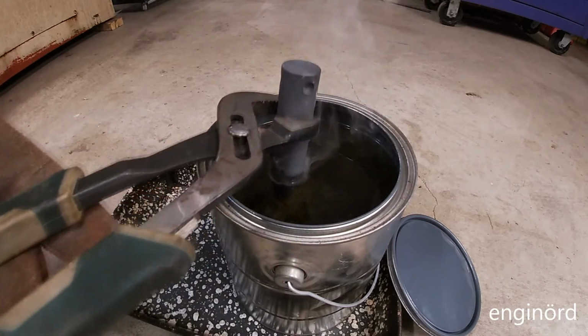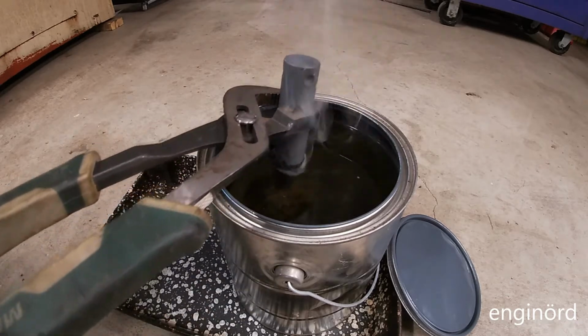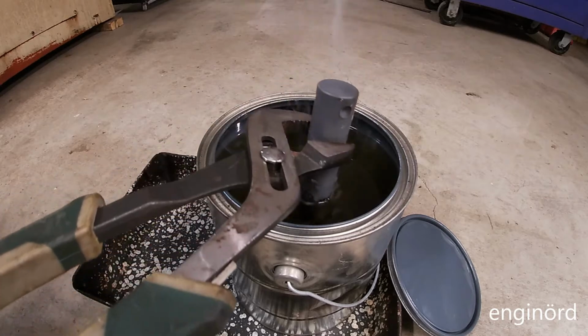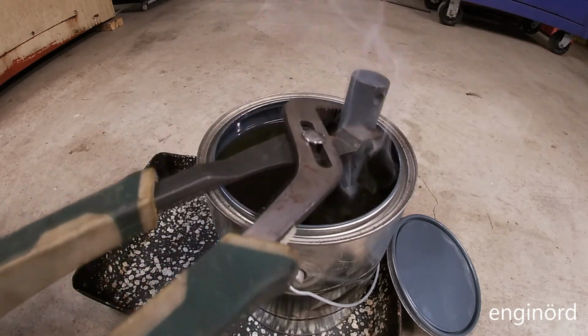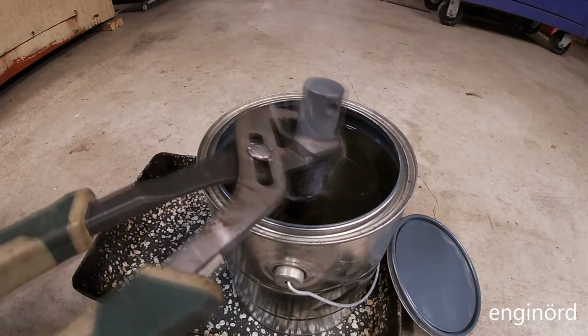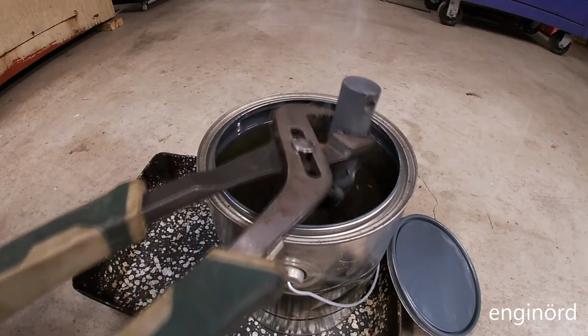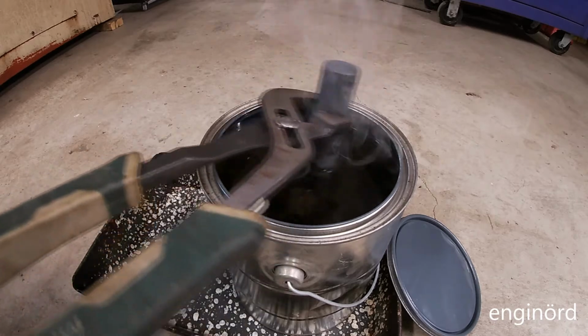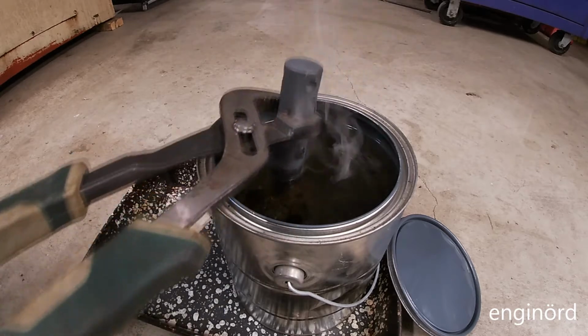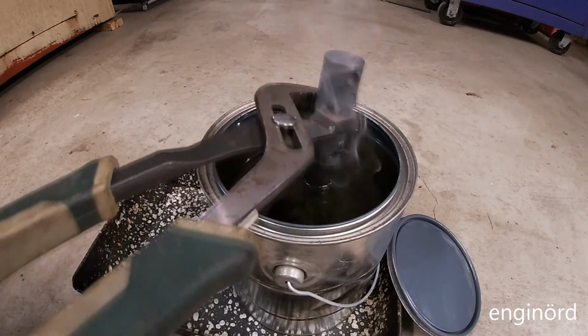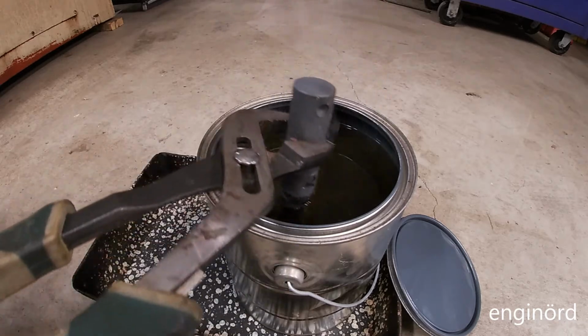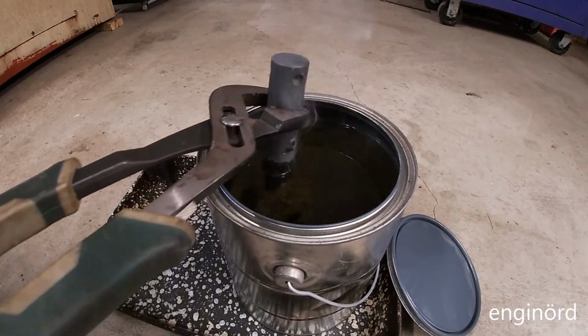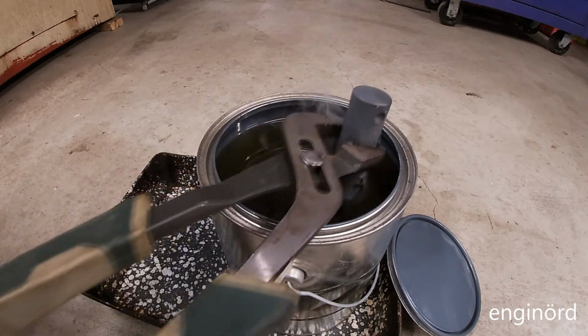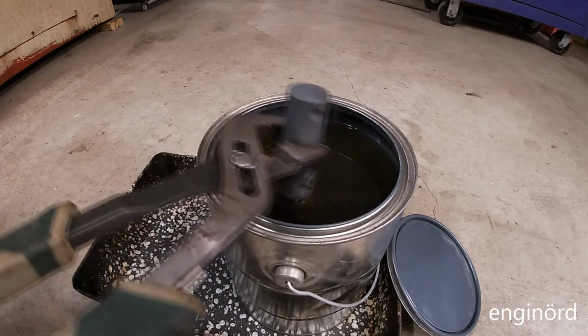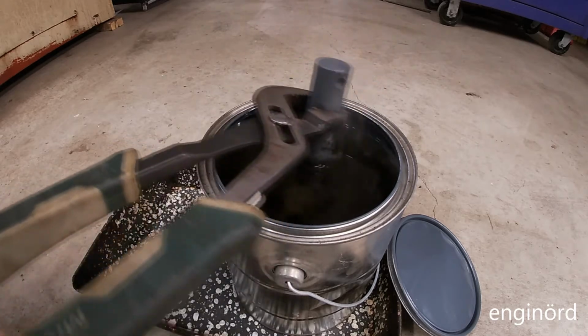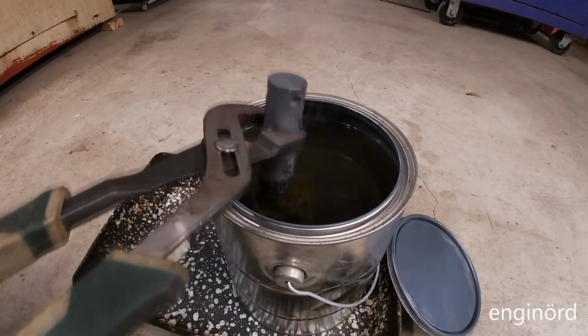And within the metal we have heat traveling from the upper part, which is still really hot, to the lower part, which is in oil. One other way to do this would have been just to hit the end with a torch and then quench it. So by doing the 3 little samples earlier, I learned that stirring the oil with the metal helps the metal cool a little bit faster, and essentially that is going to lead to a higher hardness.